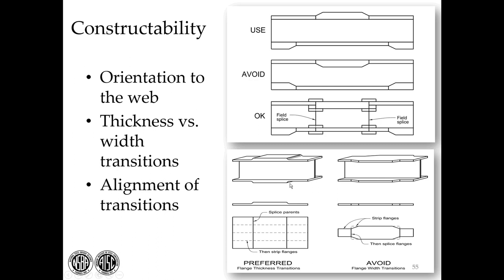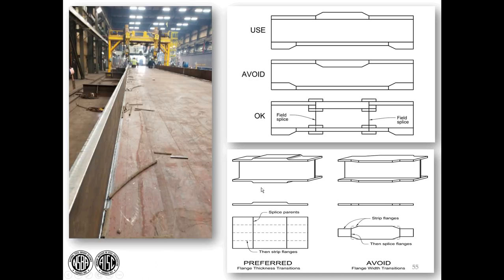We talk about a preference, if you're using thickness transitions, to avoid width transitions. It requires more material and it doesn't allow the splicing of parent plates, which is preferred. Also, to facilitate splicing parents, if you can, keep your girders and splices similar across the width of the span. So a lot of different recommendations like this. Here's a picture that emphasizes why you want one line on your girder. And most fabricators have equipment that will do this weld in one pass. If you have a thickness transition out here, well, the fabricator won't be able to use this equipment. The fabricator could do it, but it won't be constructible based on the equipment that most fabricators have.